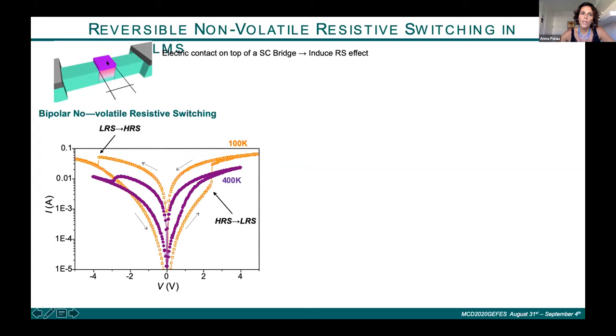We are here modulating the resistance below this gate. And what we observe is that starting from a high current, which is the low resistance state, and going to the negative voltage, when we apply a negative voltage, we lose the oxygen in the material and we induce this transition to the high resistance state, which is completely non-volatile, and it stays up to zero voltage.